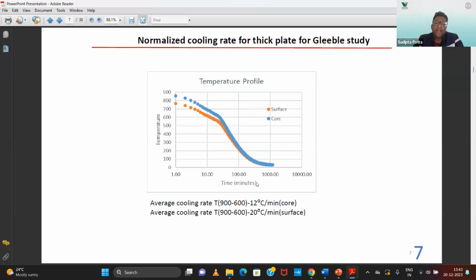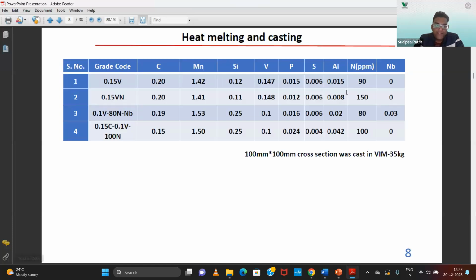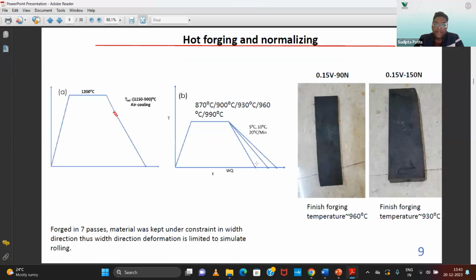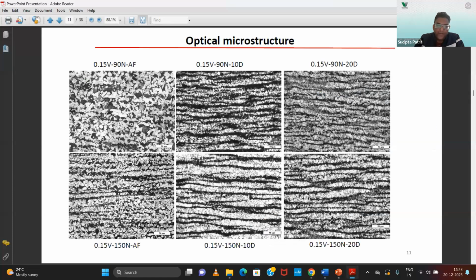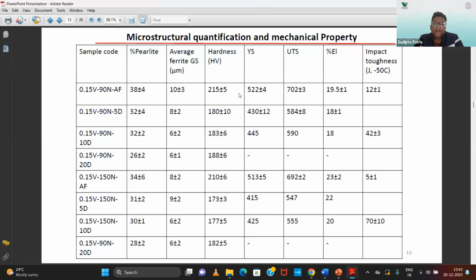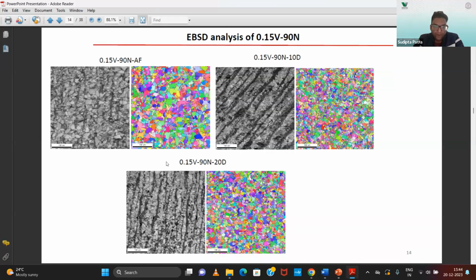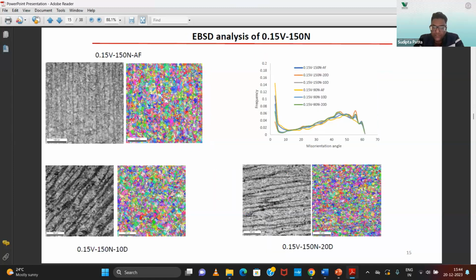Then we measured the temperature profile, and we took these 4 chemistries and melted them in a vacuum induction furnace, and then we rolled, and we got this type of ferrite pearlite microstructure. Now with this chemistry of 0.15 vanadium and 90 nitrogen, we could achieve 520 YS and 702 UTS and elongation in the as forged condition. But when we annealed it, strength was a little bit less, but we could get very good impact toughness. Here you can see with high vanadium and high nitrogen, we could get even 70 joule impact toughness at minus 50 degrees centigrade temperature. Here we are not adding any alloying element, only vanadium and nitrogen and a little bit of carbon manganese steel. The EBSD analysis also shows a high percentage of high angle grain boundaries, showing the recrystallized structure.